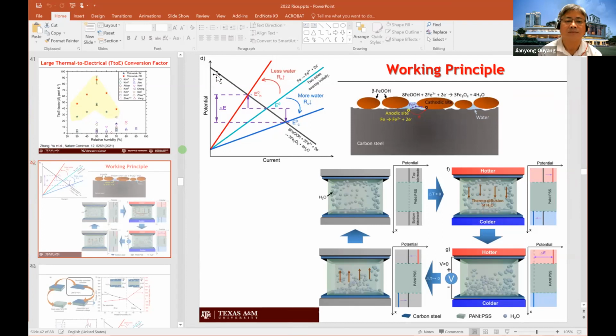So what happens here is basically the potential and the crossover between two lines. This is what we call an Evans diagram. If you have more water, then there's a more corrosive environment. If there's less water, it's a less corrosive environment. Because of that, this is a corrosion potential, where you have two reactions here. The iron becomes oxidized, and this becomes reduced, and those two lines meet at the center. This is the corrosion potential.